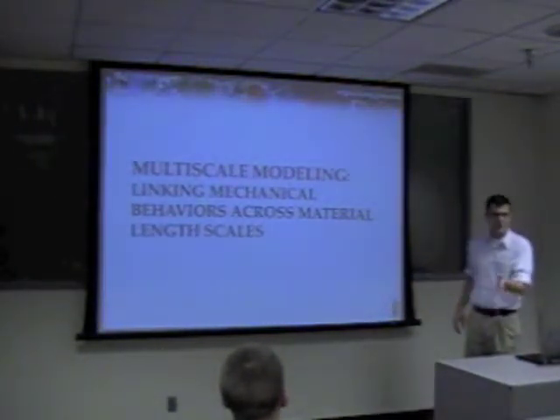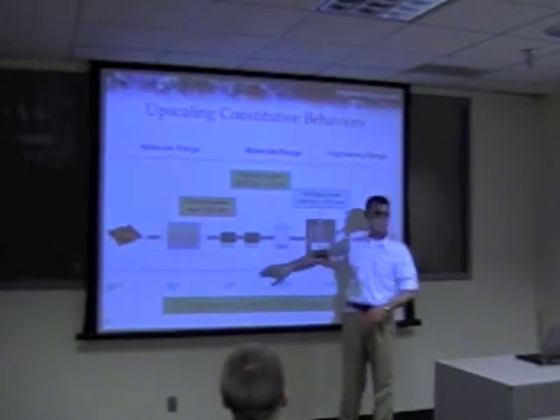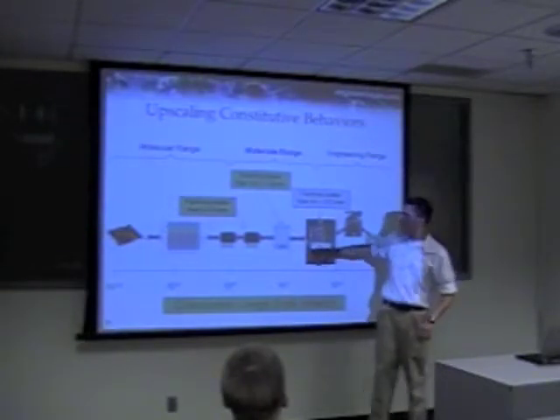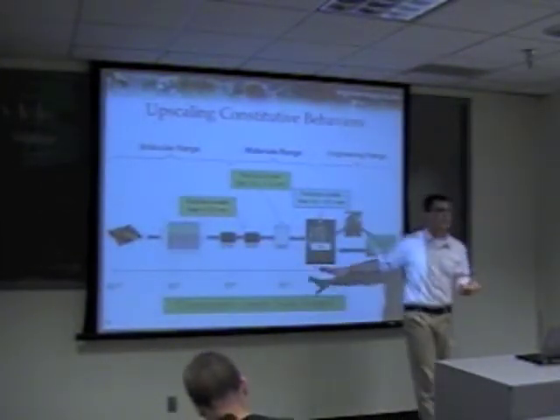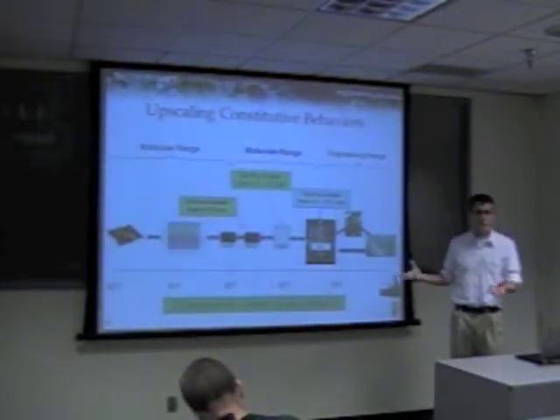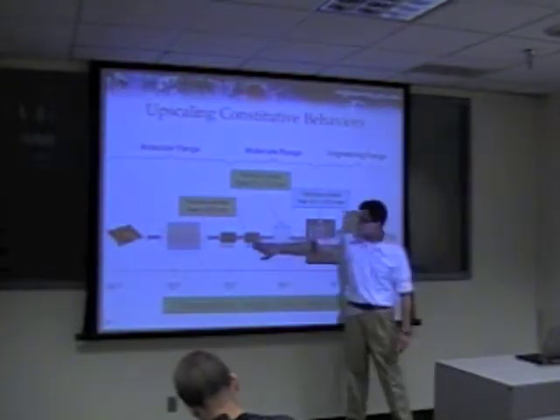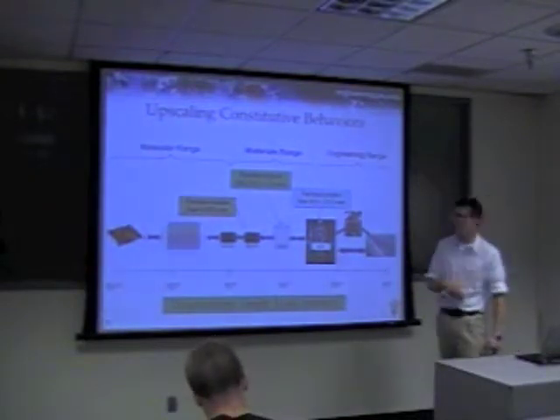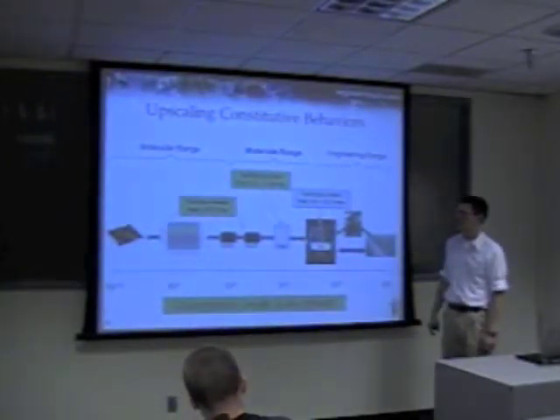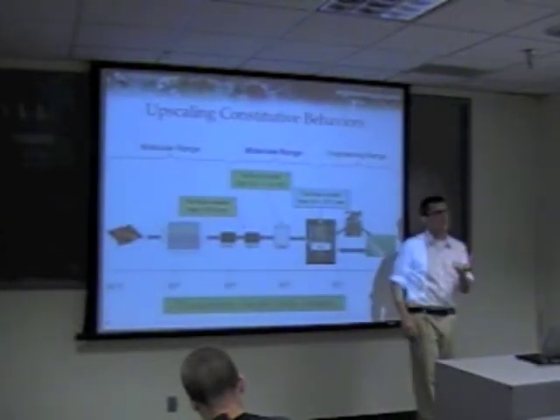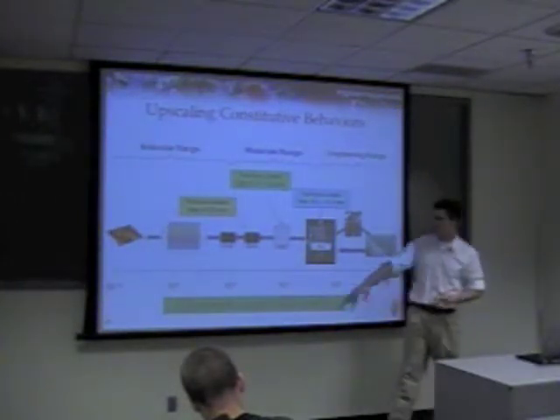So how do we link behaviors across material length scales? We're primarily focusing on the middle range — asphalt binder to asphalt mix. People have tried for years to make this link using a number of techniques, and it turns out they've all failed. So what we do instead is take an intermediate step or two. The only thing that differs between each step is the size of particles introduced into the material. For mastic, we're dealing with particles smaller than 0.075mm — a number 200 sieve. FAM, or fine aggregate matrix, is similar to mortar in Portland cement concrete, with sand-sized particles. So we're linking three scales: mastic, FAM, and mix.